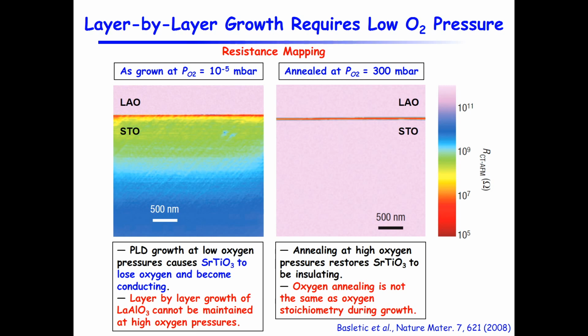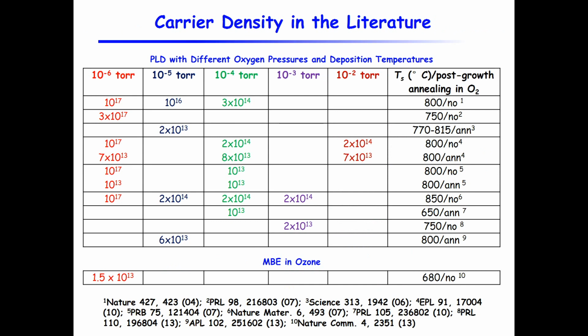Right? So if you grow the materials at low oxygen pressure, this is the scanning of the resistance mapping, and you can see that the substrate contributes very much to the conduction. So what people do is anneal the sample at higher oxygen pressure after the growth to try to fill oxygen in. Then they do see that the conduction layer happens at the interface. But the problem, I would claim, is that annealing to fill oxygen back into this interface layer after the growth is not the same as growing these materials with the right oxygen stoichiometry. Right? And that is something I think is causing the problem for all the previous reports.